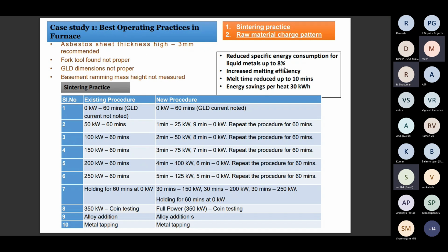In the existing practice, the sintering was followed but the asbestos sheet thickness was high. The thickness is very high; 3 mm is recommended. The fork tool was also found not proper, and the GLD dimension is not proper. The basement ramming mass height was not measured during the sintering practices, that is, during lining time.